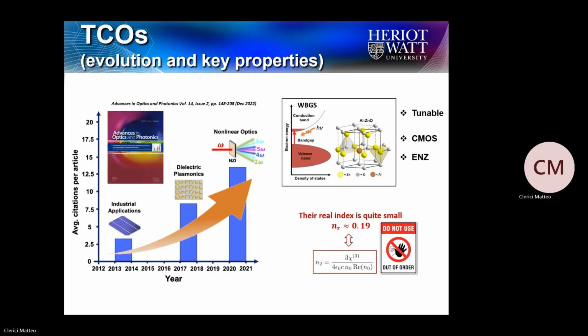However, this formula has also another interesting aspect, which is that for several years, nonlinear optics was searching for the most nonlinear material, looking for the material with the highest chi3. And then instead, when we started working with this kind of system, we sort of changed direction, searching for a material with a low refractive index. And because high chi3 is actually linked to high refractive index, it is really a sort of opposite direction.